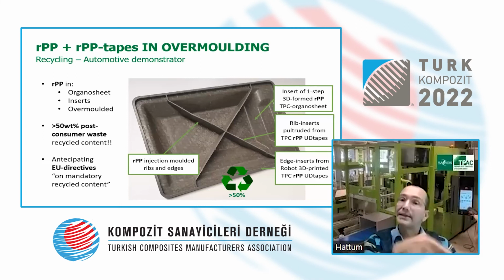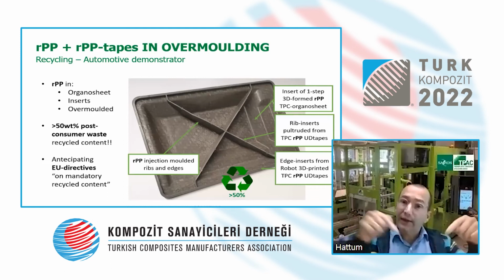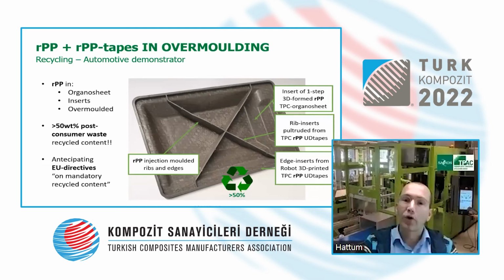Coming back to the recycling part, this is the same part, but then made out of over 50% of post-consumer polypropylene waste. So it's really completely recycled polymer. It resulted in the final part with roughly the same mechanical performance, having over 50 weight percent recycled polymer. And this is already anticipating future EU directives that the automotive industry is expecting on mandatory recycled content, the 2030, 2050 kind of legislation. It's the same part, very similar performance, and it was all developed in-house. So we're seeing how we can further follow up on this with Stellantis.